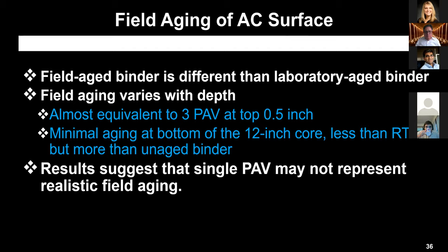So a summary of that field aging and things we learned. The field aged binder is different than laboratory aged binder. None of those curves exactly matched up. Field aging varies with depth. Almost equivalent to 3 PAV is at the top half inch. You saw minimal aging at the bottom of the 12-inch core, less than RTFO, but more than the unaged binder. And the results suggest that a single PAV is just not going to represent any realistic field aging in Illinois.